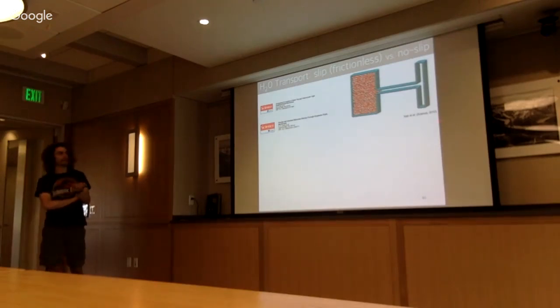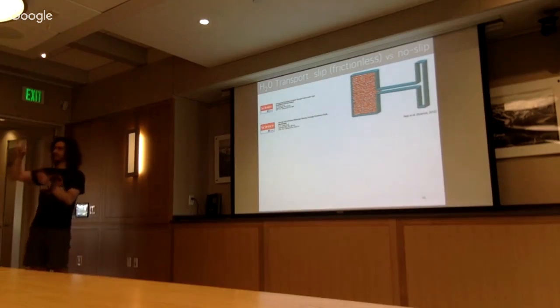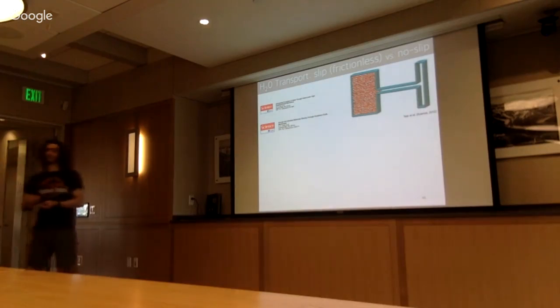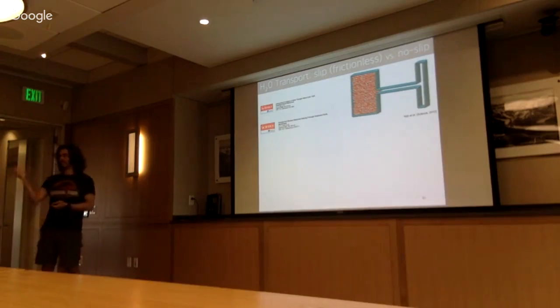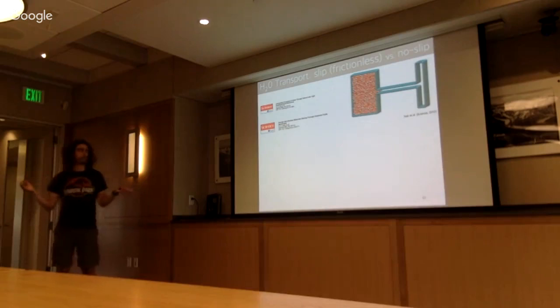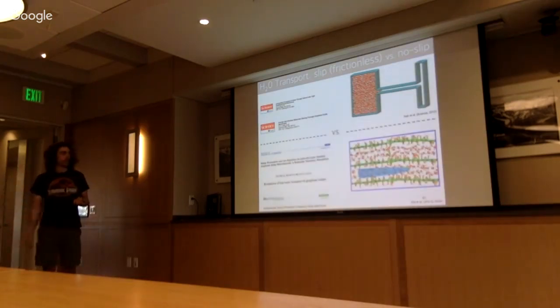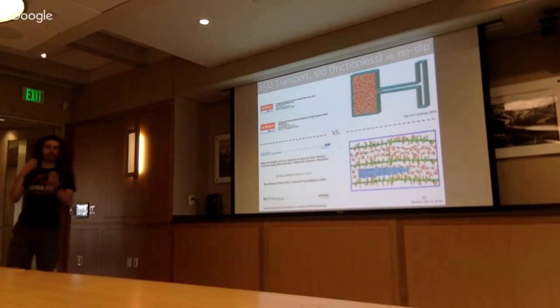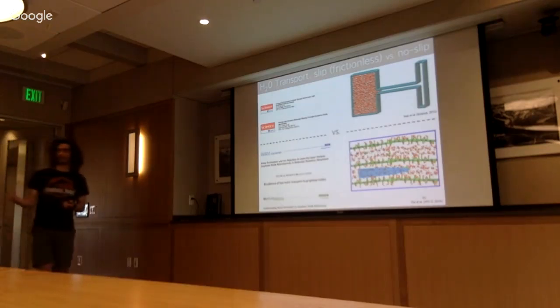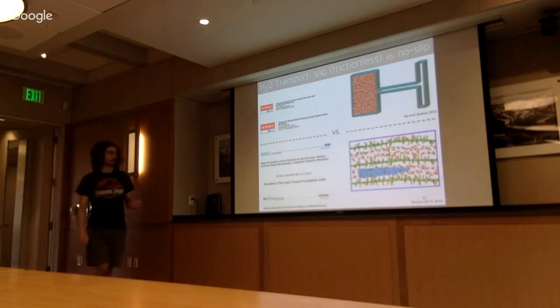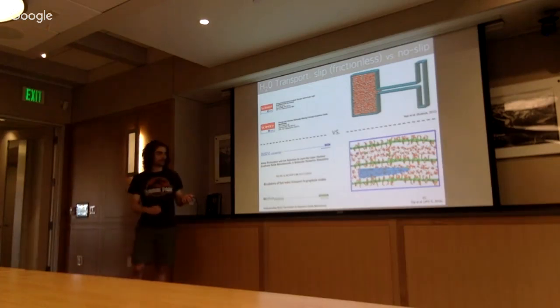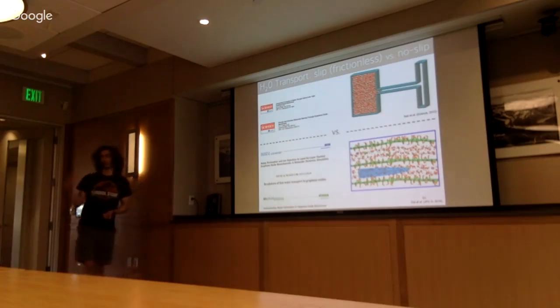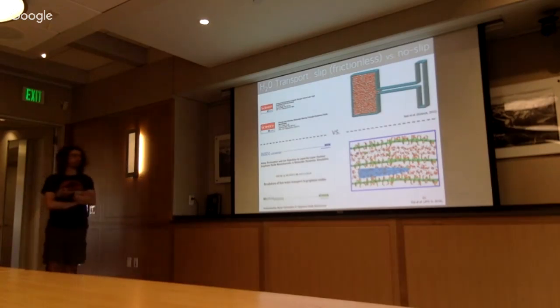On the one hand, people said that water flows inside this nanomaterial frictionless, so it doesn't feel the effect of the wall. This is similar to what has been reported in carbon nanotubes. And there was another point of view that says, no, there must be some sort of friction. You can see here with molecular dynamics results that the velocity profile is parabolic, so there is an effect of the wall.